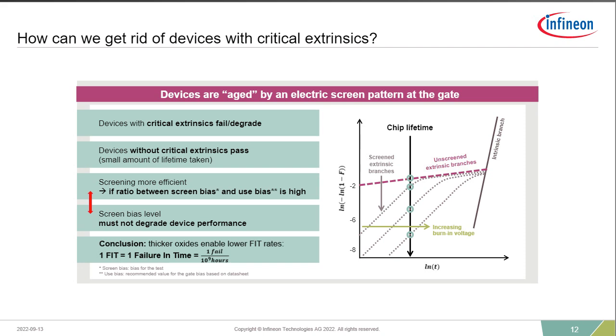One of the things that Infineon is doing is driving our gates during a screening process. We screen 100% of our devices, once they are packaged, at high gate drive voltages to eliminate basically all of these extrinsic defects. We filter those out through 100% testing. That allows us to offer a product that's extremely reliable and does not have these defects which cause early failure in the application.